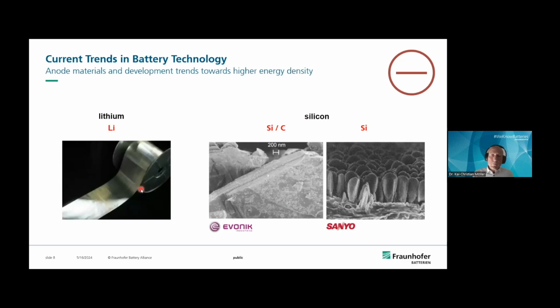In future, maybe we will see lithium, presumably in lithium sulfur cells for some flight applications, flight taxi, or for solid state batteries. This is completely different. This is a sticky, soft metal foil, which has to be put into the cells. And what is done at the moment already in small amounts is the silicon carbon composites. You can see here the graphite flake, and the white shadows here is the nanosilicon.